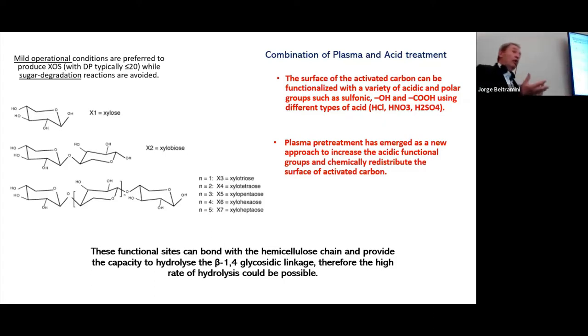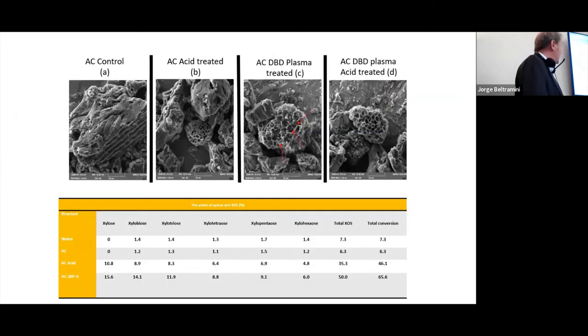We can create sulfonic groups in the carbon, and then that will give the correct acidity to break the 1,4 bond in the sugars and then create the prebiotic that we need. So at the end of the day, this is an example. This is the control, the activated carbon, and this is the plasma treated. And if you see here, we are still way ahead. We produce nearly 50% selectivity of the prebiotic with a total conversion of 65. Still it is not good enough, but we are working on that.